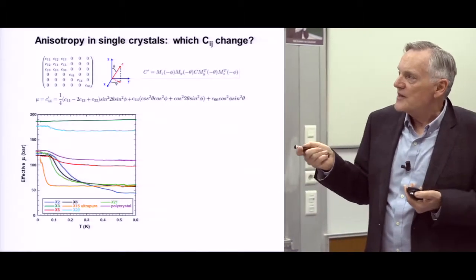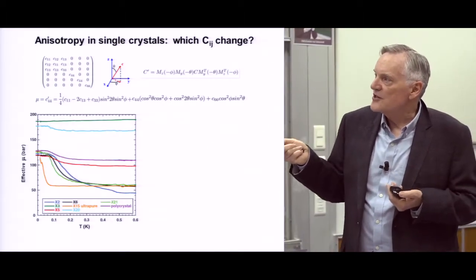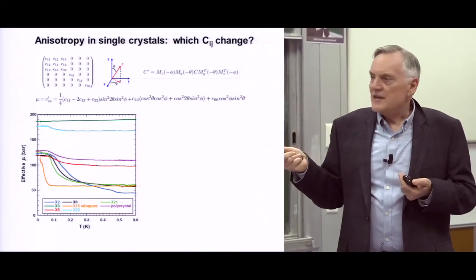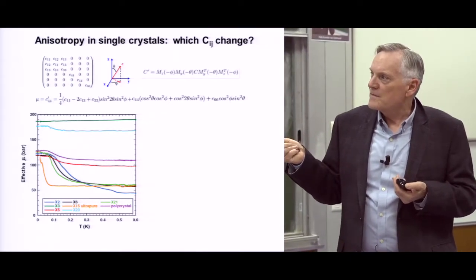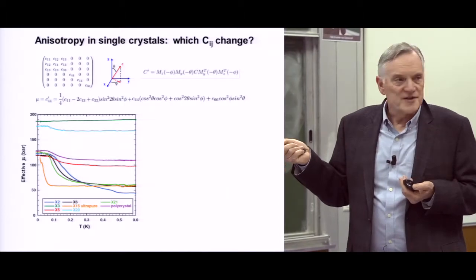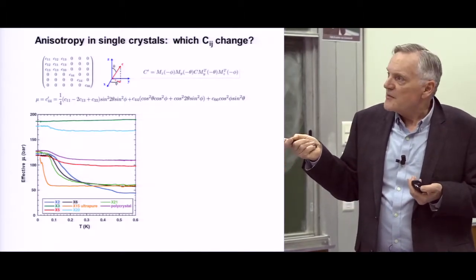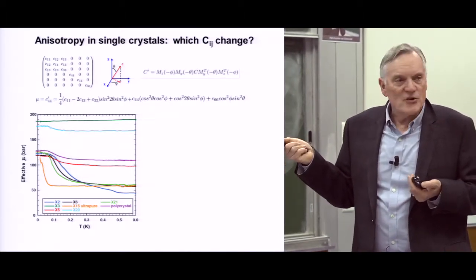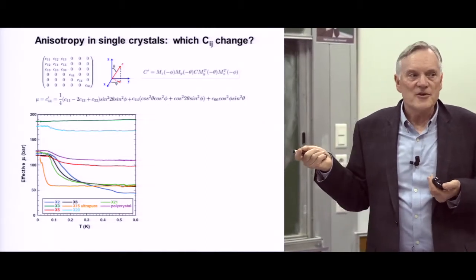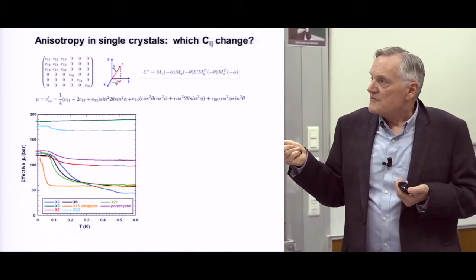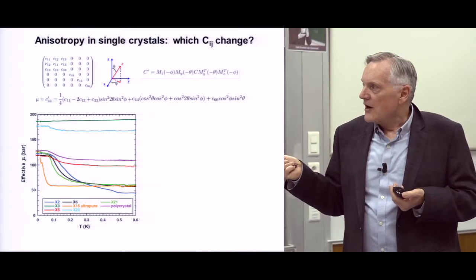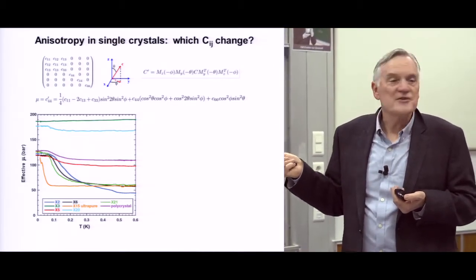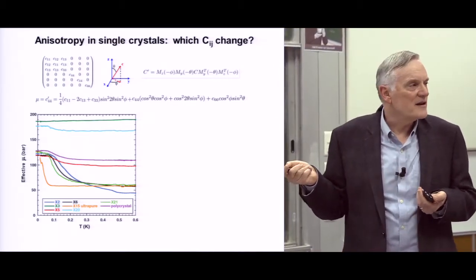And so if you do this and grow a bunch of crystals, here's the shear modulus. These are all different crystals. And you see something quite interesting. They're not all the same. They're all single crystals grown in the same way, just different orientations. Some of them are very stiff. One of them is very stiff. And not only is it very stiff, it doesn't soften at high temperature at all. Others soften a little bit. Others soften a lot, you know, soften 60%. They have less than half the shear modulus at high temperatures.